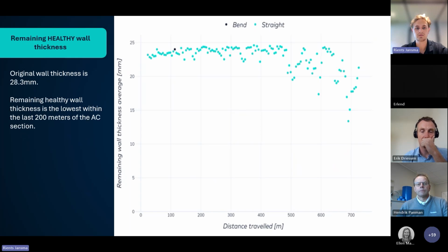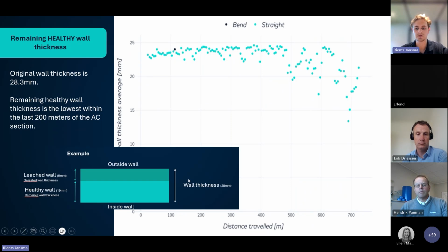So here you could see it as the graph has flipped. So it's the remaining wall thickness, and the distance traveled at the bottom. So at the end, you can see that in the last 200 meters, again, the remaining wall thickness is the lowest because of the leaching. It's the remaining healthy wall thickness. Like I've explained before, the wall thickness remains the same. The healthy wall thickness is lesser because of the leached wall you can see above.